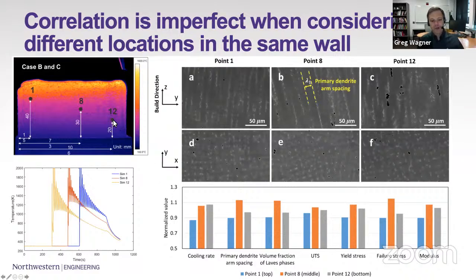Toward the bottom of the build, the cooling rate is the highest because that's where you're closest to the substrate. You're conducting heat away most quickly. Toward the top of the wall, you've already built up residual heat, so your cooling rate has slowed down. And our temperature histories predict that. By the way, when we compute the cooling rate here, we're talking about the solidification cooling rate.